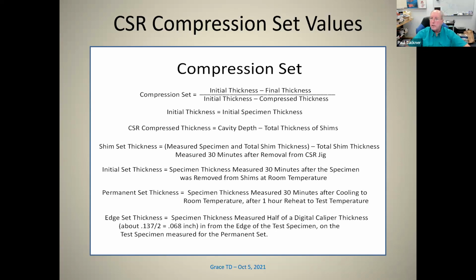Then you let the specimen sit for 30 minutes at room temperature to recover, and measure it at that point. Then you put it back in the oven at test temperature for 60 minutes, take it out, let it cool back to room temperature for 30 minutes, and check it again.